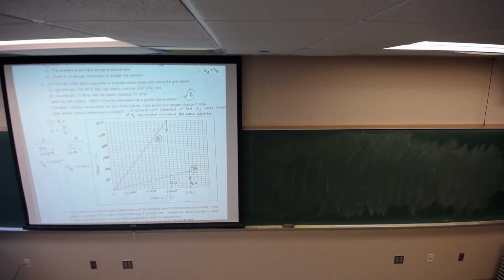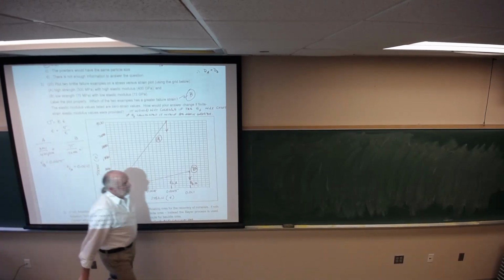Now, how would your answer change if the finite strain elastic modulus values were provided? We don't have to come back to that. If your strain at failure was the same, it doesn't change, correct? But if you are calculating your strain at failure from elastic modulus, then your calculated strain at failure would be much greater. Good? Because you would have a lower elastic modulus than this value, and you would go to the same stress level. So we do it for the top one, it's easiest.